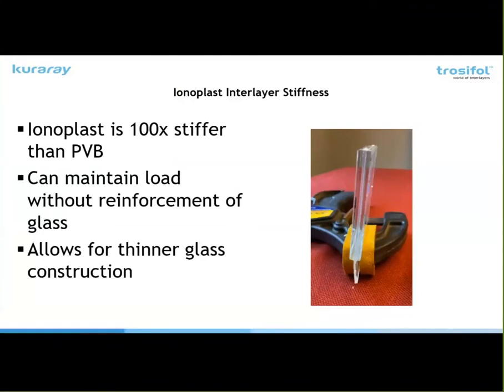Now with ionoplast, it was invented in the 1990s after Hurricane Andrew struck Florida, and it was developed initially for improved hurricane resistance and windblown debris resistance. So it's 100 times stiffer than PVB. It's got 5 times the tear strength, and it can maintain the load even without the reinforcement of the glass. So this may allow for thinner glass construction. That may be important if you're doing larger glass, because as you go larger and larger, it gets heavier, and if you can reduce the thickness, that can help offset some of the weight.